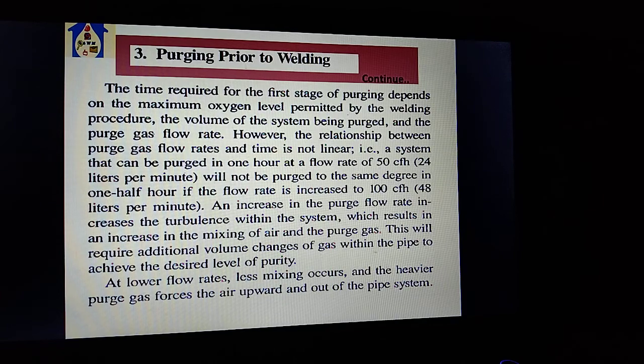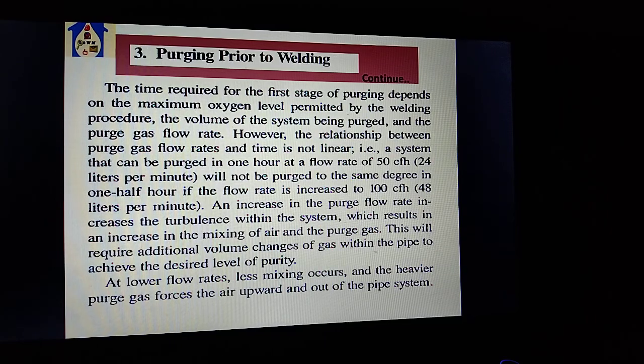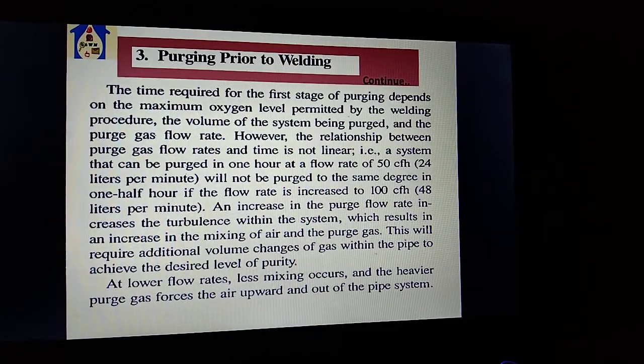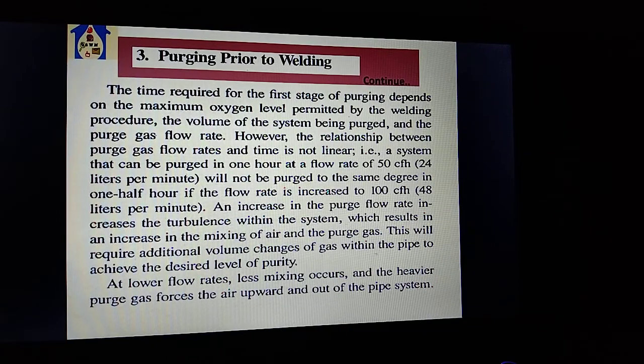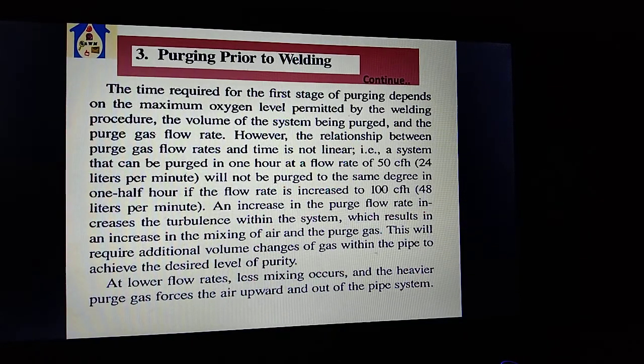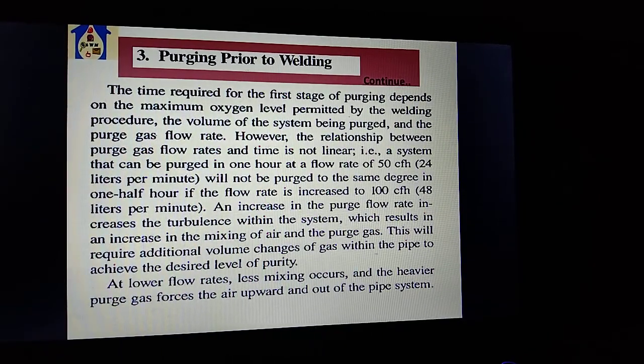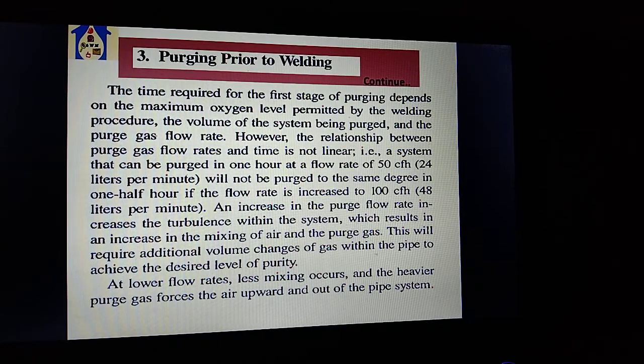However, the relationship between purge gas flow rate and time is not linear. For example, a system that can be purged in 1 hour at a flow rate of 50 CFH, 24 liters per minute, will not be purged in one half hour to the same degree if the flow rate is increased to 48 liters per minute.